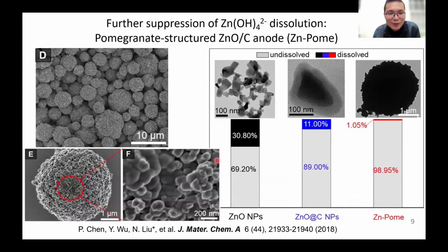We further assembled these particles into a secondary particle to further suppress the dissolution, because now if you have some zincate in the middle, it will be very hard for it to go across so many layers all the way to the electrolyte outside. If you compare the amount dissolved from these particles, this is better than this, and then the secondary particle is even less than the primary core-shell particle.